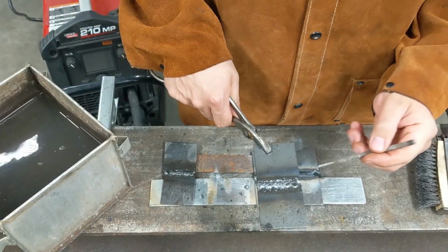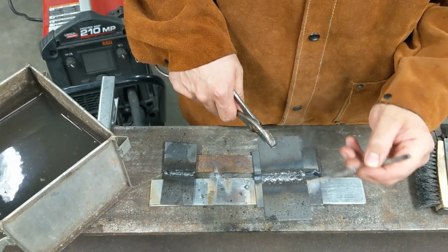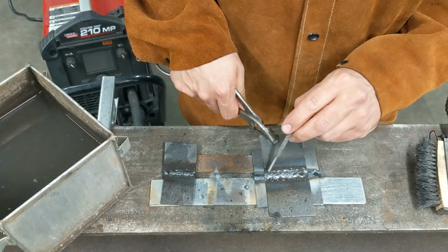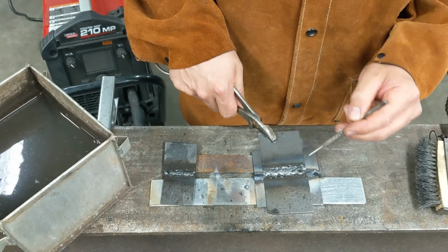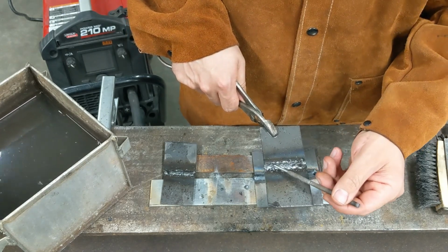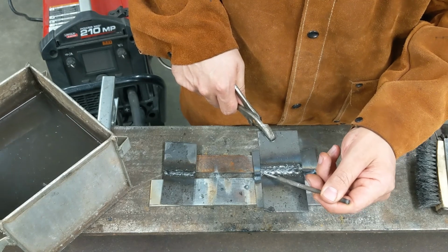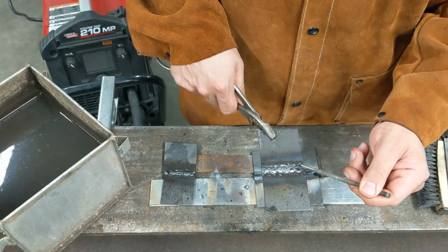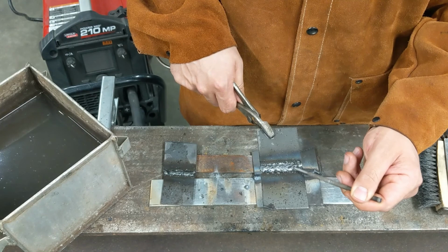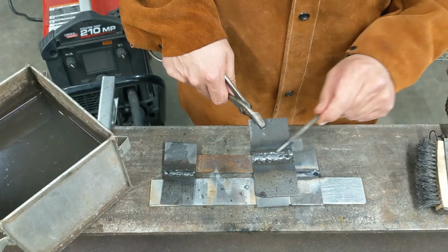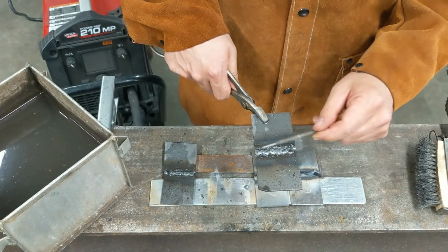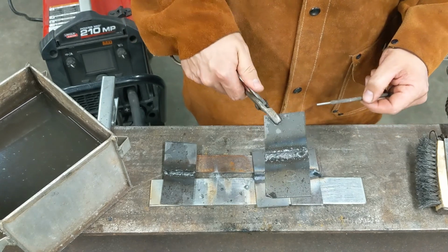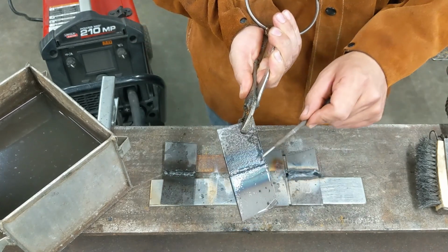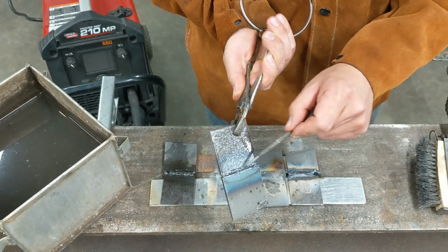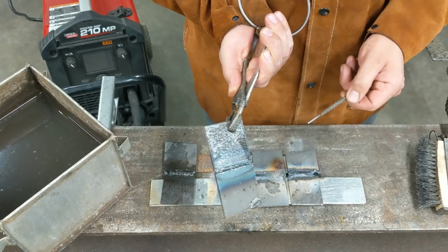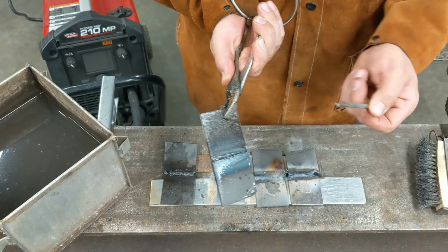Our second sample has a much wider bead now. There's enough amperage that the weld pool is starting to really melt into the material. In addition, you can see in the second sample that where we started, the weld bead is relatively narrow and high. Where we finished, it was relatively wide and shallow. That's because as we welded, we heated up the workpieces. That allowed the metal to diffuse more into the base metals. You can see here that there's just a few points where the metal started to peek through. We didn't have full weld penetration, but we're certainly getting there.